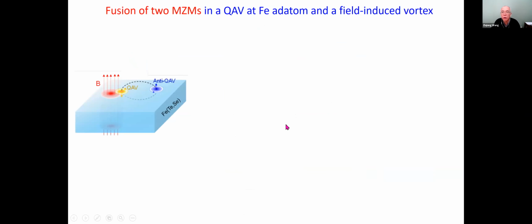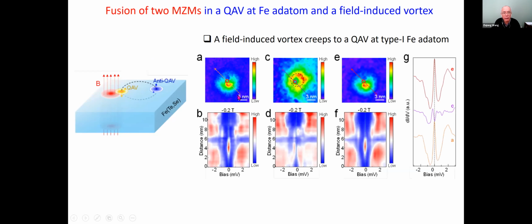And there is also initial data for observing the interaction of a quantum anomalous vortex-induced Majorana zero mode and a B-field-induced zero mode. As you see here, this is an impurity-induced zero mode. And a vortex creeps in if you put this thing in the magnetic field. And these two things fuse, you lose the zero energy state. And if you wait, this vortex hops away, the field-induced vortex, they move, it hops away, and you recover what you had before.